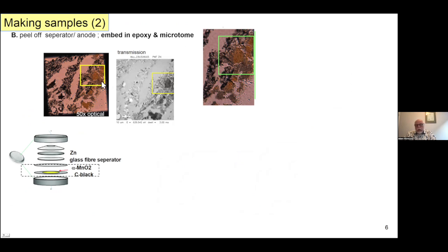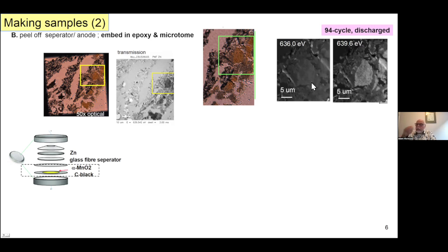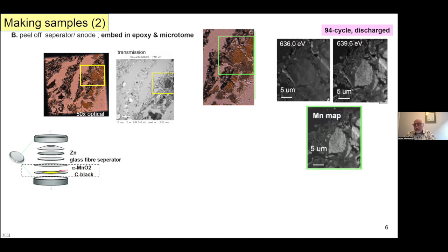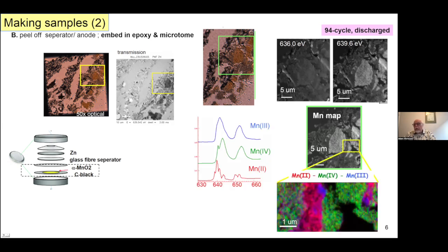So we went in and with the STXM looked at this area, which was at the interface between the carbon and the manganese dioxide, several magnifications. And then we started to do the spectroscopic measurements, looking at below the manganese edge and on the peak of the absorption of all of the manganese oxides. The difference of that, what we call a stack map, just very nicely shows you the spatial distributions of the manganese present. We then went in on a smaller area where we could then do a full stack where we can trace out and see the spectroscopic differences between manganese 2, 3, and 4 oxidation states.